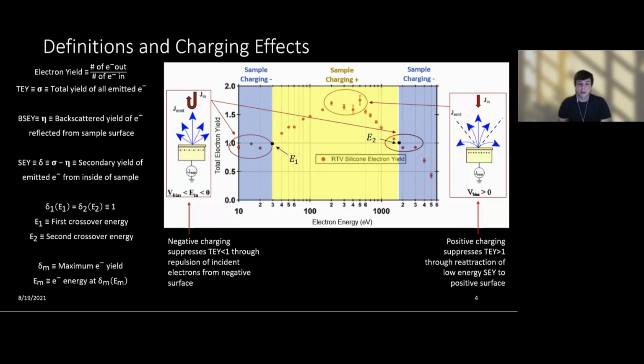Our group employs numerous techniques in order to minimize these charging effects for insulators. We utilize enhanced low fluence methods for insulator yields that allow us to conduct measurements at low currents down to less than 1 nanoamp per square millimeter and pulse widths of less than 4 microseconds, containing just under 1,000 electrons per square millimeter. The experiment also contains an in situ surface voltage probe, along with the ability to neutralize sample charging with low energy electrons and UV radiation.